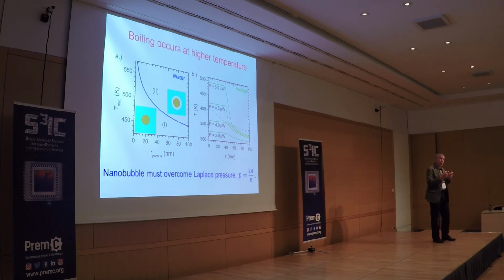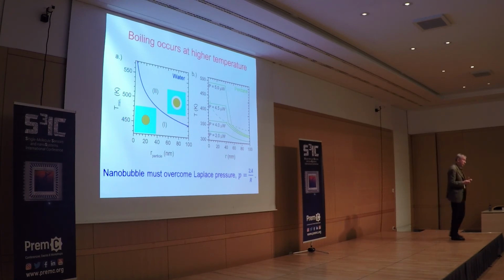So you have to heat much more than you would if it were a macroscopic object. So this boiling requires more power, and you can measure that. This is a simulation, but you see that as soon as you form the bubble, of course, the bubble is made out of steam, a very bad heat conductor. So there is a jump in temperature.